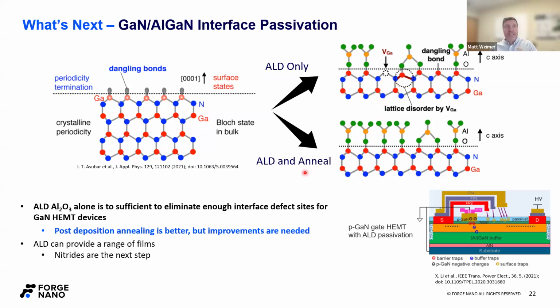But what they found is if they did a light anneal, say, 400 C, that they were able to improve things more. There was some, we'll say, mobility of those gallium atoms to fill in those voids. So you just get a much more regular lattice at that interface, right? So again, this is the application that exists today. Again, this is for the GaN HEMT device. That passivation layer is shown in blue. So there's maybe an AlGaN layer there on top. It kind of depends on what you're making.